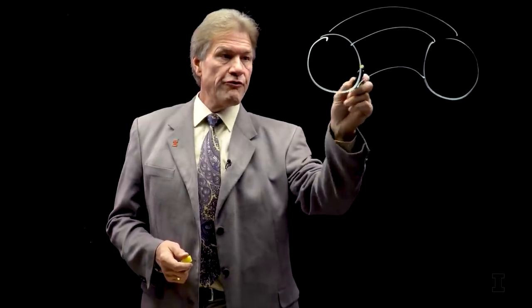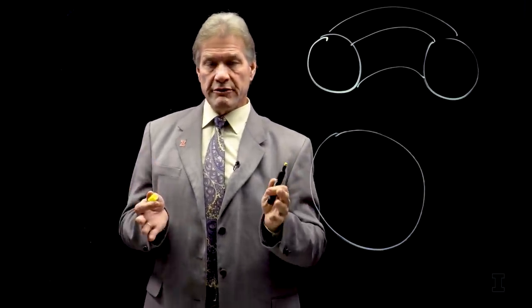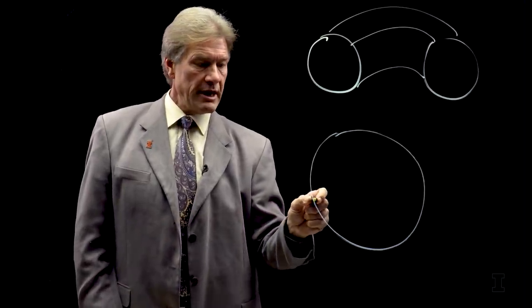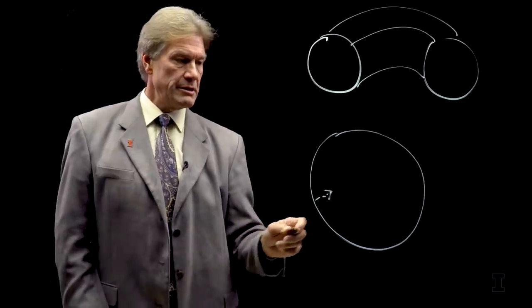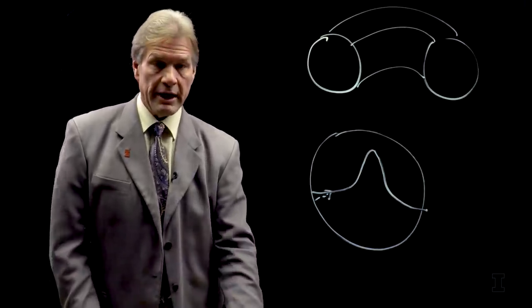So what does this do for our fusion reactions? Let's imagine we've got a toroidal fusion device. So it kind of goes across here, and here's the other cross section of it, sort of a donut cut in half. But let me just concentrate on one side of this. Let me just concentrate on the profiles across here. So I'll make this a bit bigger. In a standard fusion device, without lithium walls, because I have this return of the cold gas, if I drew the temperature going across here, it's going to be cold at the edge and only really hot in the middle. And that means only this very center portion where the temperature is high will participate in fusion.